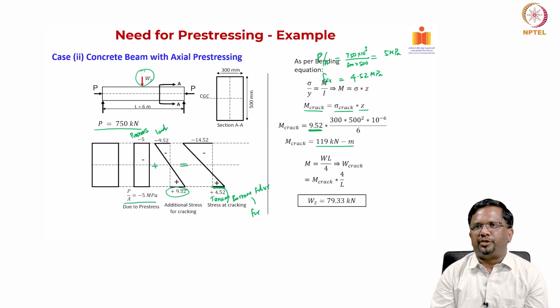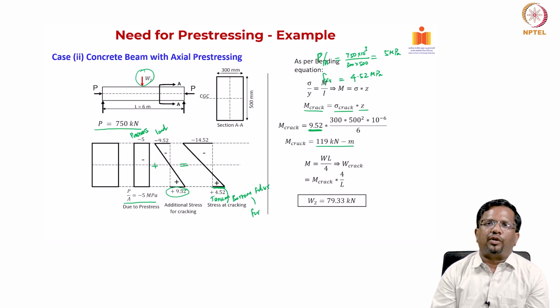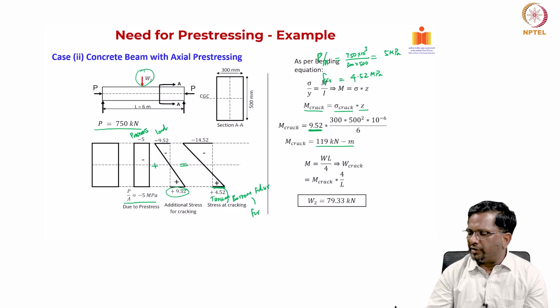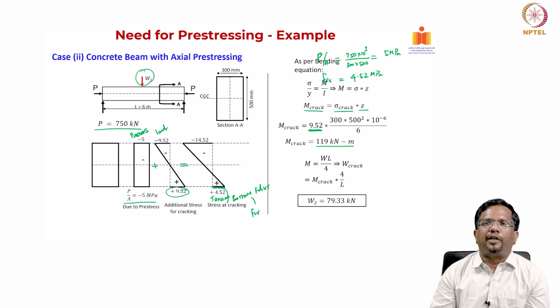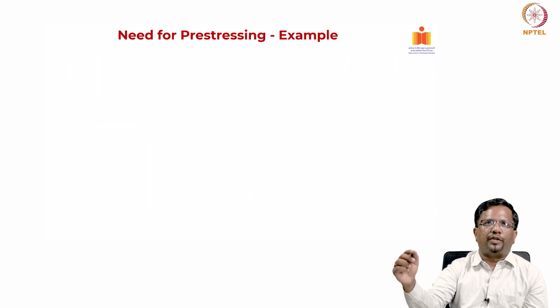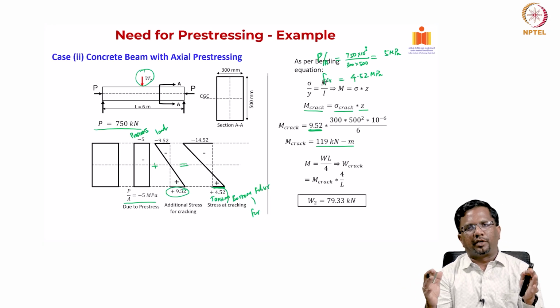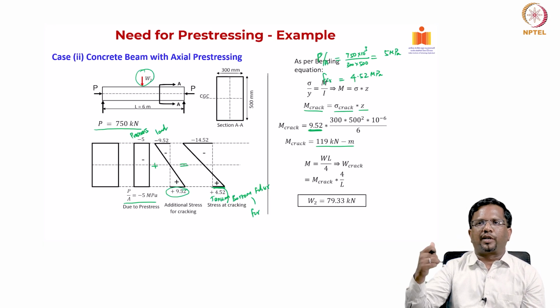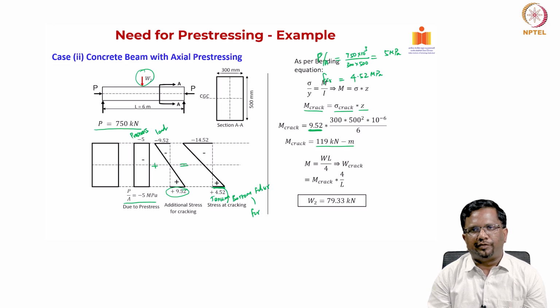Now, if you substitute and calculate the load required to crack, you can see here it has become 79.33, which is more than double that of what we had for plain concrete. So, you can see here, just by applying this 5 megapascal compression, the load at cracking has increased significantly.